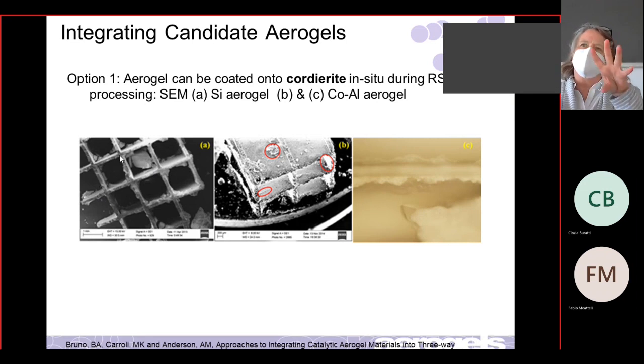And so we had the idea, well, what if we go in, yeah, you can't fill the whole thing because then you wouldn't get any flow. Well, you could if we could get good flow through aerogel, but the flow coming out of your car is too much to go through. But can we coat it? The idea is, can you get aerogel to stick right around the surface? And it's porous, so can you get the aerogel just on the surface? You don't need to fill it, just like a layer. And so we did do that, and we had some luck with doing that, during the rapid supercritical extraction process. We cut up a piece of this, and we put it in our mold with the aerogel solution, and we processed it. And so we had some luck with that. We did get some aerogel material in there.